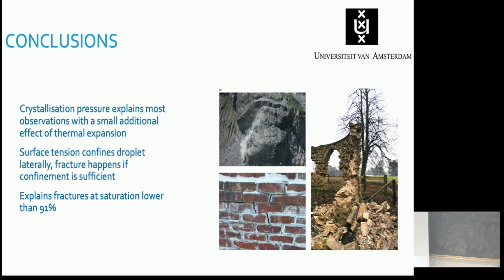Because they are confined. And so this easily explains what I wanted to explain in the beginning, namely if you have these liquid pockets in porous materials and they do freeze, you don't need to have a saturated porous medium to actually get damage. In fact, we even seem to see that there's an optimum droplet volume fraction, or droplet volume in any case, that would lead to the most damage.